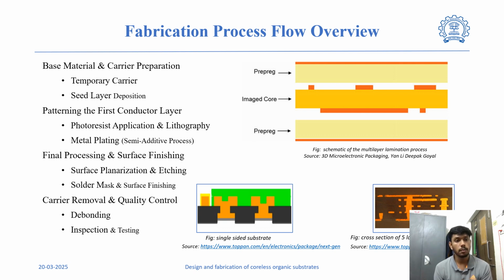The via formation can be done by mechanical drilling or lasers, as laser will give the smaller vias with high precision to ensure fine features, but mechanical drilling will give the cost-effective solution to form a via for the size in between 30 to 100 micrometers. These vias will serve as electrical connections between the different layers in a multi-layer substrate.